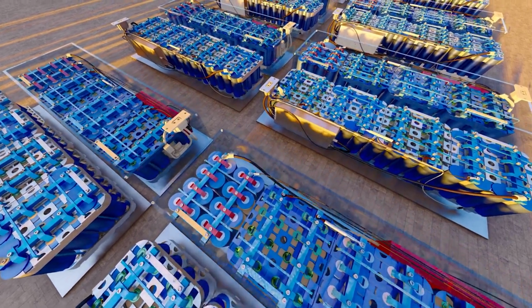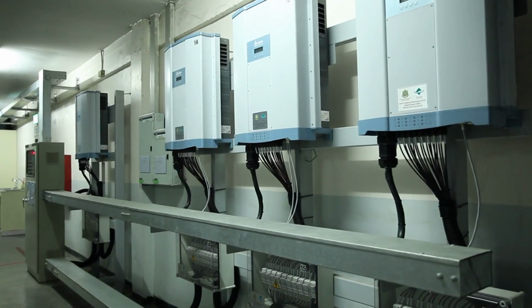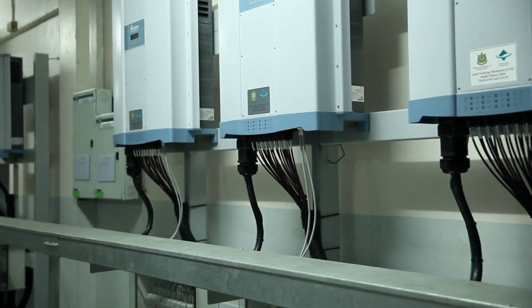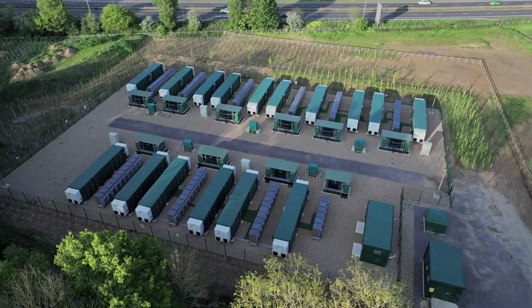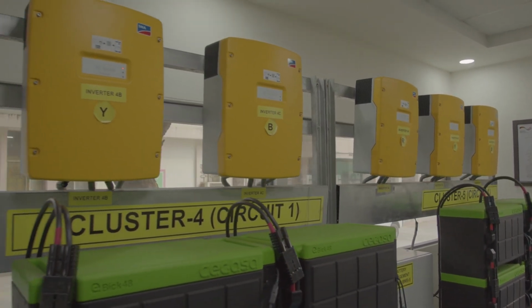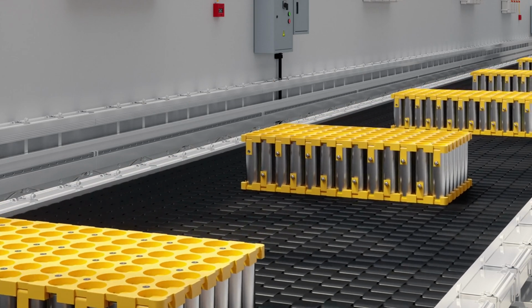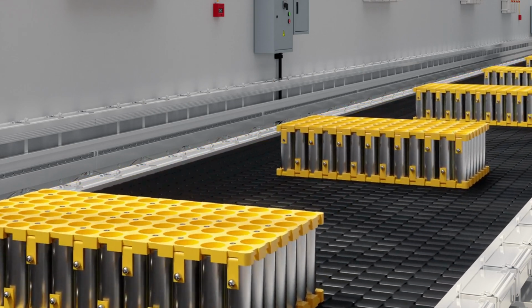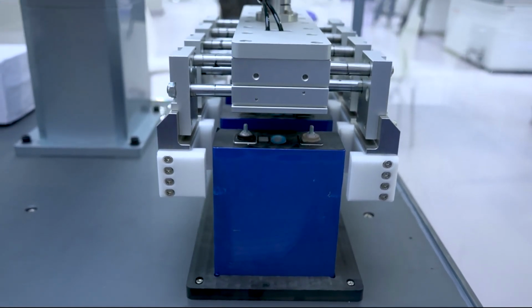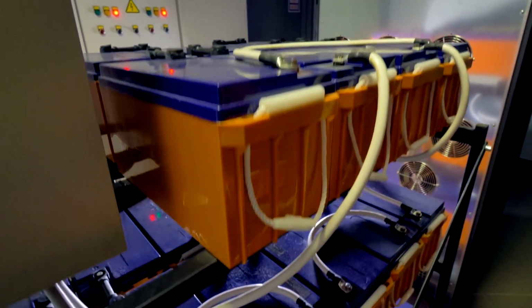Clean rooms, dry rooms, and contamination control for solid electrolytes. Many solid electrolytes react with moisture, and even small humidity exposure can change surface chemistry. Particles are another quiet killer. A speck of debris can create a local short, a weak interface, or a crack that grows during cycling. Joint facilities usually separate spaces into clean and dirty work, with a dry room for the most sensitive steps. In plain terms, the target is very low humidity and stable conditions, day and night. Consistency matters as much as how dry it is.